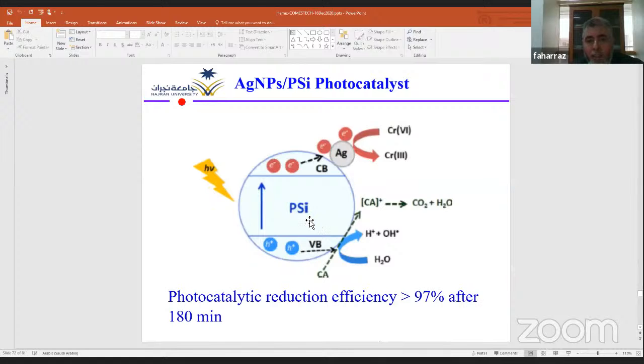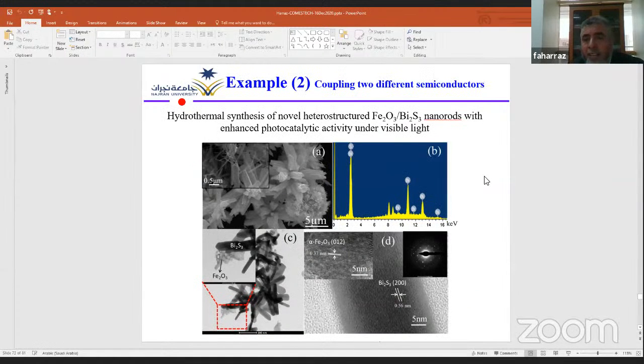And this is an interesting result of photoreduction of chromium-6 to chromium-3. Under illumination, some electrons are excited and move to the conduction band. The silver captures those electrons as an electron sink and uses them during the photoreduction of chromium-6 to chromium-3. The holes remain at the valence band of the porous silicon and can contribute efficiently as oxidant. In this work, we got a photocatalytic reduction efficiency of chromium-6 to chromium-3 above 97% after 3 hours.